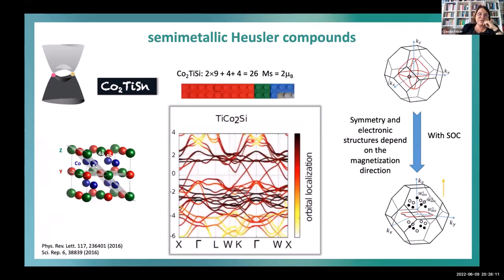Since we are now also on topology, in 2016 there was a prediction from Hasan's group and Andrei Bernevig that they simply recognized in one of the Heusler compounds, a cobalt titanium silicide, which has 26 valence electrons and 2 Bohr magnetons, that even if you do a fully relativistic calculation, you see that there are nice crossing points.